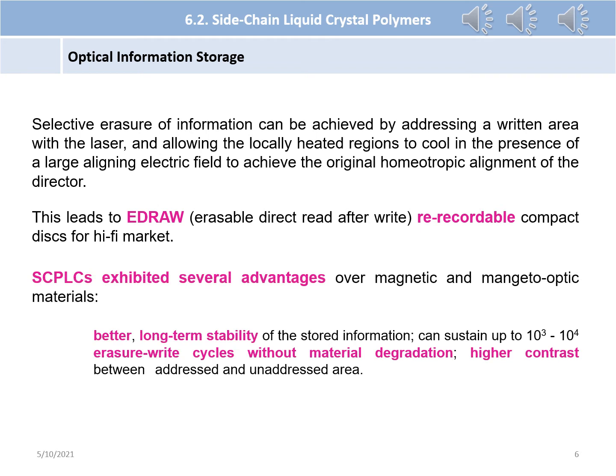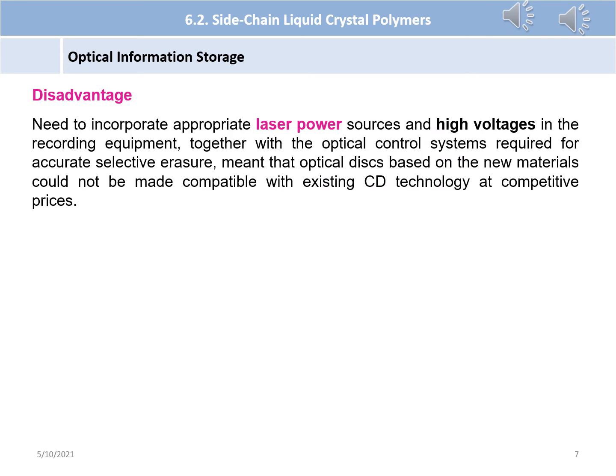Side-chain polymer liquid crystals exhibit several advantages over magnetic and magneto-optic materials. They have better long-term stability of the stored information, which can sustain up to 10 cubed to 10 to the power of 4 erase-write cycles without material degradation, as well as higher contrast between addressed and unaddressed areas. The disadvantage of this E-DRAW is the need to incorporate appropriate laser power sources and high voltages in the recording equipment, together with the optical control systems required for accurate selective erasure. This meant that optical discs based on the new materials could not be made compatible with existing CD technology at competitive prices.